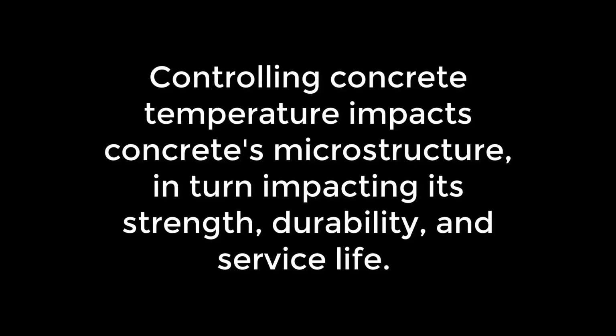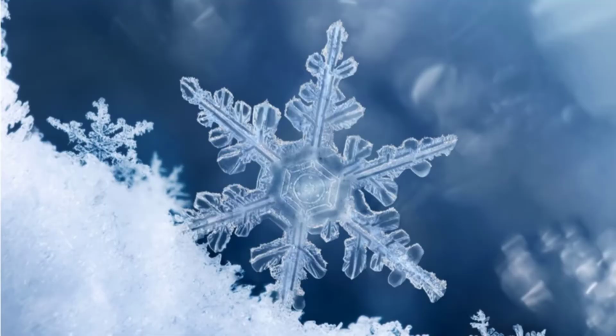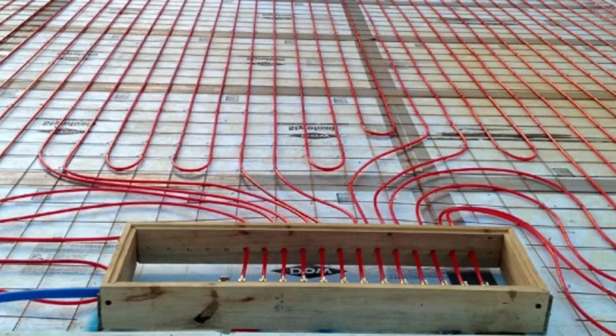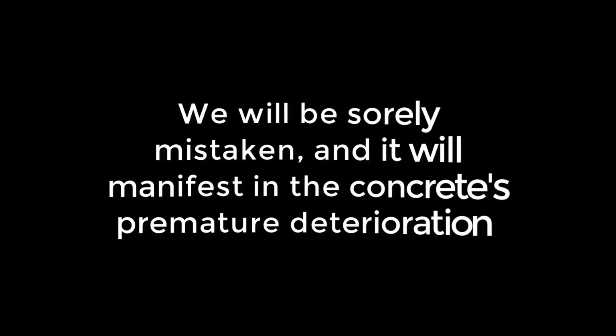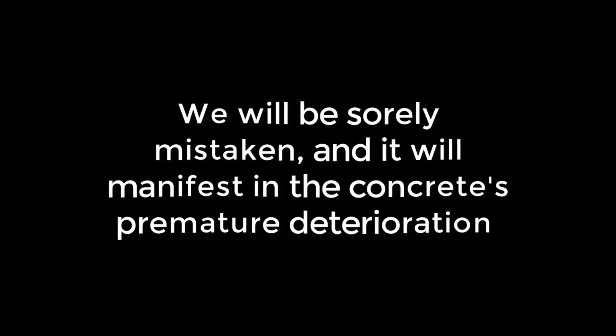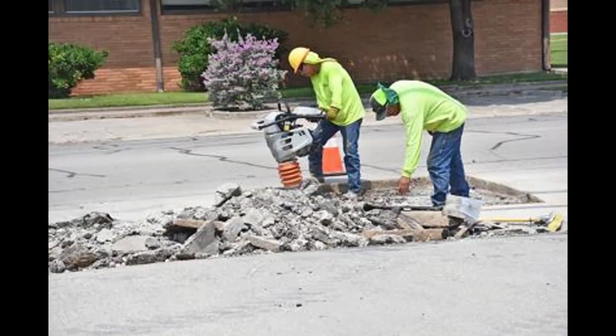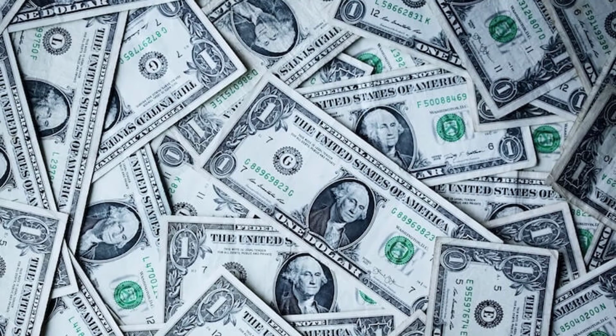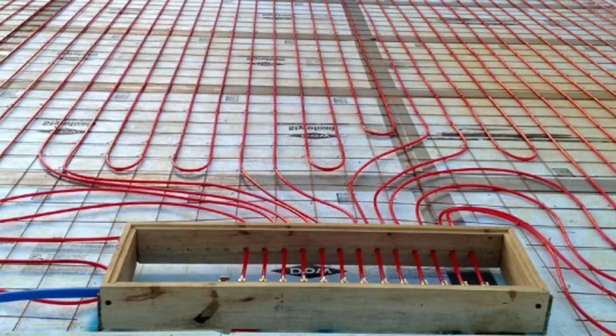And if our expectation is that a concrete that goes through a freezing and thawing cycle will still be as hard and tough as the concrete that's controlled with a little bit of effort and a little bit of work, we will be sorely mistaken. And it will manifest in concrete deteriorating prematurely and us having to come back and really just answering a warranty and service issue. And that is ripping out an in-service slab is extremely expensive. Much more expensive than putting a hydronic system down that is very easy to make with some garden hose, with some blankets, a heating element, a tub, a tank, and a generator, or at least a freaking outlet.